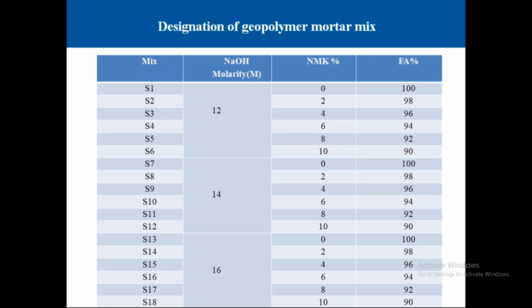Then we have given certain names to the mixes. To determine the compressive strength of fly ash based geopolymer mortar, 18 mixes were prepared by using different molar concentrations, which were chosen as 12 M, 14 M, and 16 M. Cement and water present in the cement mortar were replaced with fly ash and alkaline activator solution respectively. The alkaline activator solution to fly ash ratio was kept as 0.4, sodium silicate to sodium hydroxide as 2.5, and water to solid ratio as 0.3. In all we have casted 216 specimens of geopolymer mortar, varying molarity of the hydroxide and percentage of NMK with fly ash.